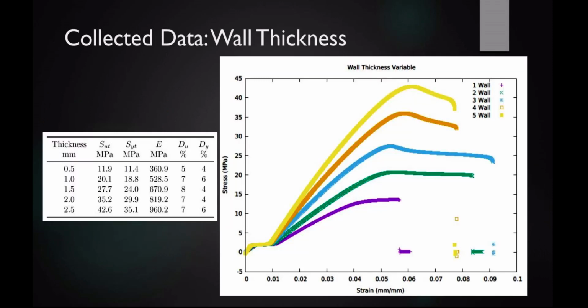Some of my collected data, again, we tested as per ASTM D638. It's a standard tensile property, so these are all tensile properties for that polymer. This is for the wall thickness, and we see a linear increase as we increase the thickness of the wall in all ultimate strength, yield strength, and modulus of elasticity. There's not a huge correlation in terms of ductility. We're not seeing much correlation there.